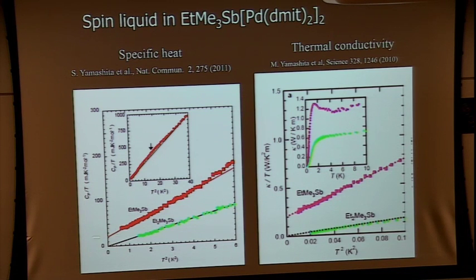It has a finite intercept. And the right-hand side figure shows the thermal conductivity divided by temperature. This non-spin liquid material shows a vanishing value, but the spin liquid material has finite values at zero temperature. So for these materials, the specific heat measurements and the thermal conductivity measurements agree with each other. And so people believe that these materials are a gapless spin liquid. There is no experimental data showing a finite gap in these materials.